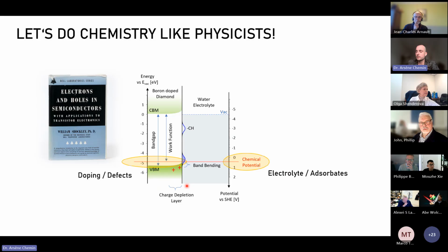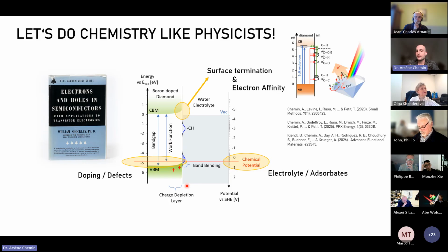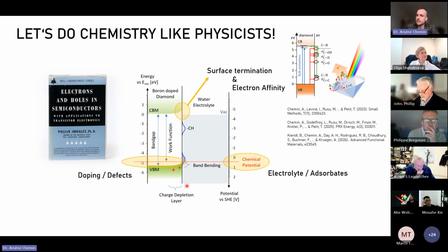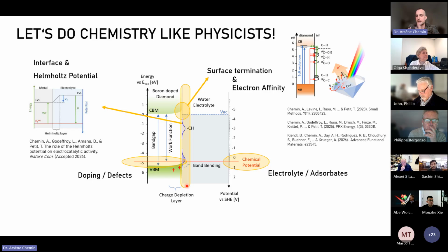On the other side, well, it's basically chemistry. So you have the electrolyte, often water, which is well defined, or some adsorbate like CO2, water molecule, etc. You will have at the surface of the diamond the surface termination, so hydrogen, oxygen, nitrogen, fluorine, that will change the electron affinity, and so the position of the valence band and conduction band. And finally, you will have the equilibrium at the interface. And this actually was not so well understood until lately.